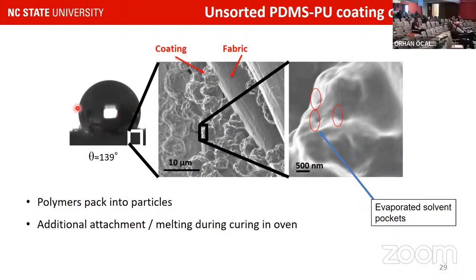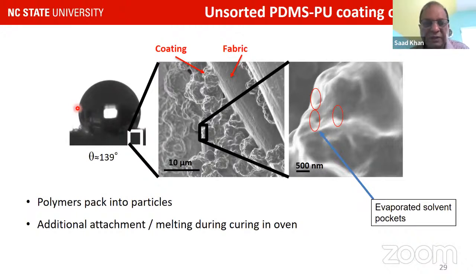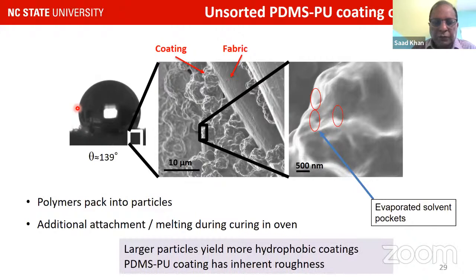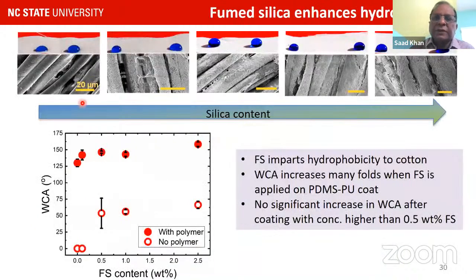It packs in well. And so one of the issues is, can we make this even more hydrophobic? Can we make this abrasion resistant? And can we make this so that it's sort of breathable? So what we wanted to do was play around with the PDMS PU coating, which has some inherent roughness. We also wanted to see if we can do something beyond just the polymer and block polymer itself. One of the ideas we had was to use fumed silica.